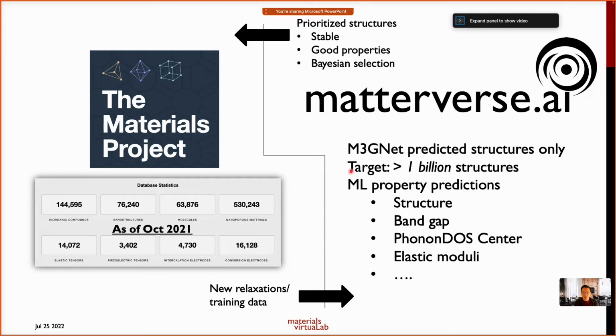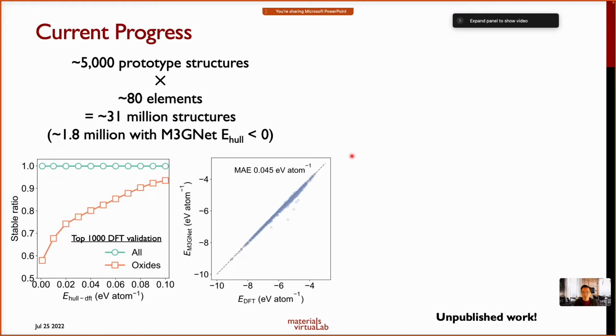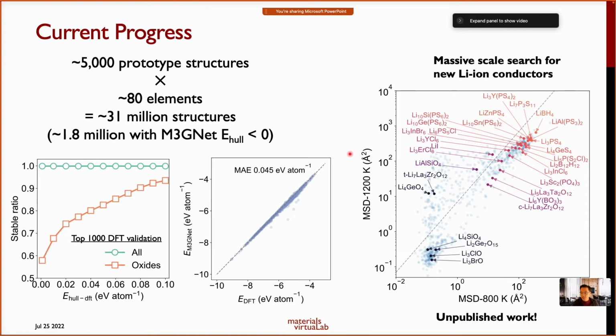Okay, so this is the current progress. Today we have already done about 31 million structures. This is generated from 5,000 structural prototypes, with 80 elements. Out of these 31 million structural prototypes, we actually get about 1.8 million with M3GNet predicted E above hull of less than 0, and we actually took about 2,000 of them to confirm with DFT calculations,